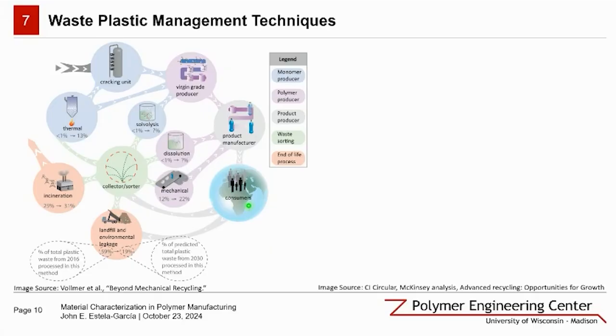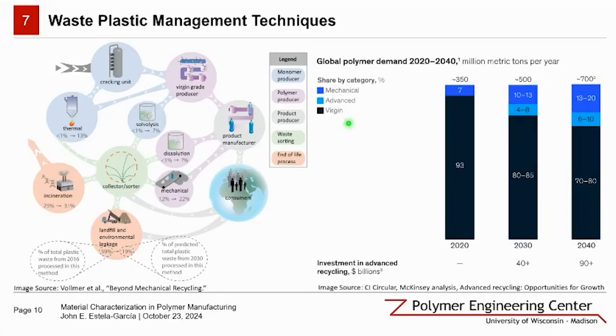So we can turn our attention to predicted polymer demand. These projections on the right are both challenging but promising. Here in 2020, we see that there was a demand of 350 million metric tons for plastics, with only about 7% of that being supplied by mechanically recycled materials. Fast forwarding to 2030, we're looking at a demand increase to 500 million tons. Recycled content is projected to increase significantly, tied together with advanced recycling. This could contribute to 20% of the demand. However, this still leaves 80% still coming from virgin materials.